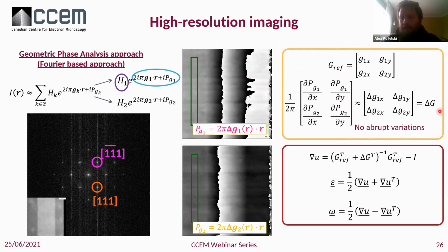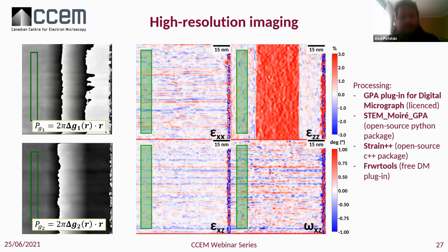So once you have these two matrices, you can then estimate the gradient of the displacement field and find the strain and the rotation in a similar manner as we just talked about before. But here the equation is not using directly the lattice spacing, but just the evaluation of the G vectors over the entire image. And that's the key difference between GPA and these real space methods. So what we gain from that is that we don't have an individual evaluation of the geometry variation. Now we have a phase component that is measured at each pixel of the image.